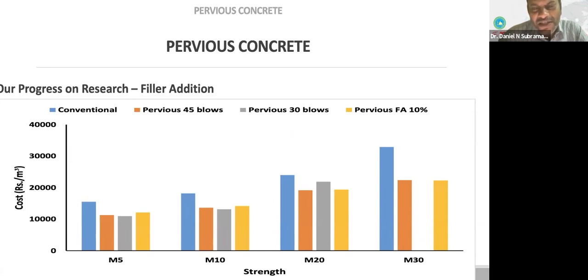So this is the cost, for example, for a particular design, say M5, M10, M20, M30, if you're using different concrete: conventional concrete, pervious concrete with 45 blows, pervious concrete with 30 blows, pervious with fly ash addition of 10%. So this is the cost analysis we have. The cost is much higher for conventional, and we have significantly less cost for the others, especially when we go to the higher grade concretes.